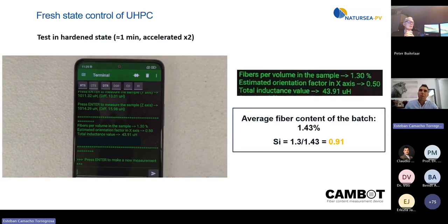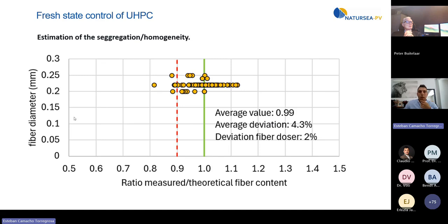So it helps us to understand what is the good flowability that we need to have to control a good dispersion and homogeneity of the fiber content. Here you can see a plot of this segregation index related also with the fiber diameter. In general, we can assume that the higher the fiber diameter, the easier is the segregation of the fiber in the concrete. But as you see, the average value is almost 1. This means that the device that we use to measure works well, because on average, the content of fibers is the same as what we add to the batch.